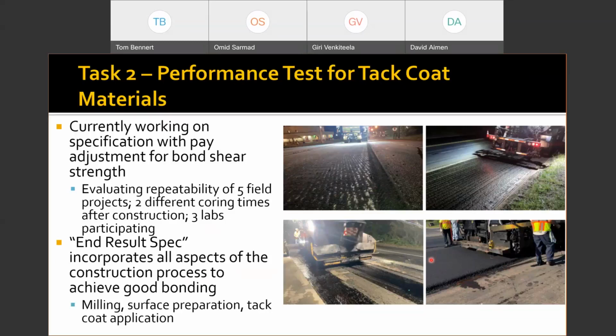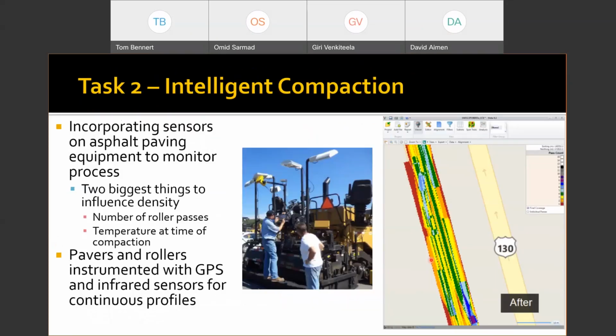So what we're trying to do is help develop an end result spec. We're looking at a core bond strength test. We're doing some round robin testing now on 5 different projects at 2 different times after construction to see if aging is significant. There are 3 laboratories participating to get an idea of what the repeatability is and what sort of criteria we're looking for on this sort of material, this sort of practice. But a critical part in the construction process of our asphalt pavements is ensuring we get that bond.